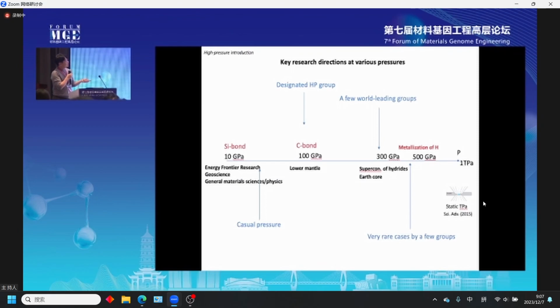Around 500 gigapascal, only very rare cases in the world report reaching this pressure. At this pressure, we can see the metallization of solid hydrogen, because solid hydrogen can turn into a metallic state, and then it becomes a very high TC superconducting material. We believe that the interior of Jupiter should consist of this metallic hydrogen, in a very high superconducting state. So it could be related to high pressure, but also related to planetary science.